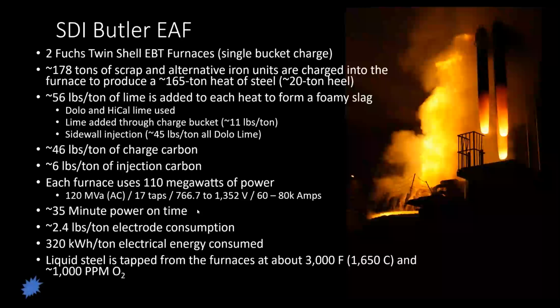Our power on time is 35 minutes. We're looking at about 2.4 pounds per ton of electrode consumption. That adds into your carbon, since our electrodes are graphite, which is carbon.